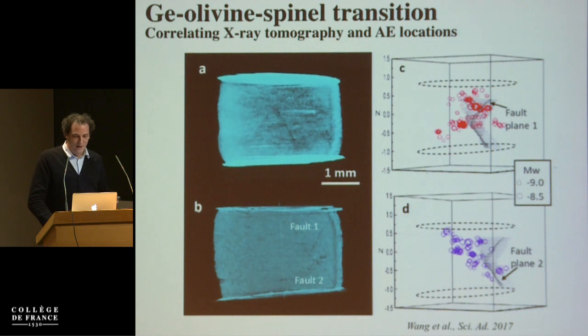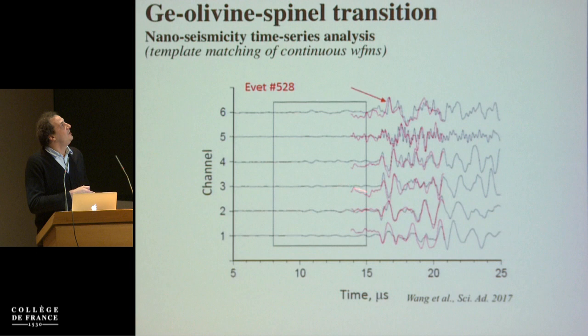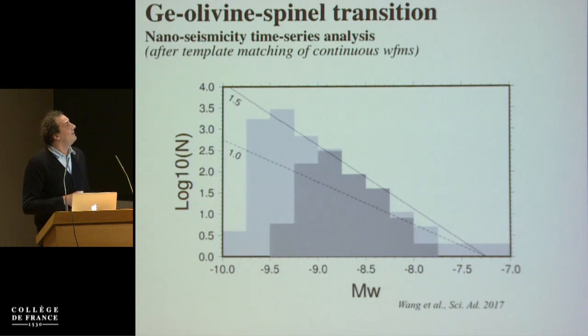So the second thing he said, well, since we have one continuous record, we can do template matching. And so he took one event and he basically rescanned the continuous waveform. And once he did that, this is our initial histogram of magnitude distribution that I showed with the b-value that we initially measured here, and that he remeasured better with a different number. He was able to get many thousands more events, especially very small ones, and we get a different b-value. But now we have enough events that we can look at the temporal series during the experiment.